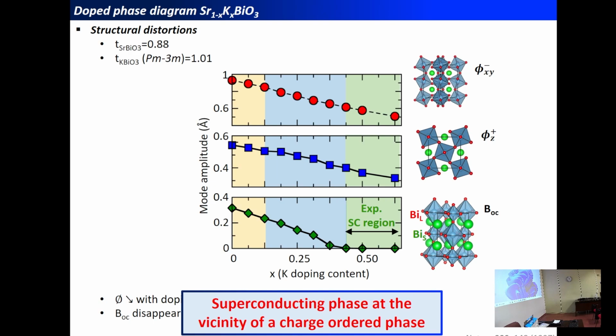Yes? Just one question. If you actually integrate the densities of states, what is the actual value of the charge disproportionation between the two bismuths? If you look at the sphere integrated charge, it's not a very good indicator, because when you integrate the density, there is one sphere that will have more oxygen contributions. So it does increase the number of electrons you would expect to have on this bismuth cation. But from the sphere integrated charges, you see the asymmetry. So it's around 0.4 electrons, something like that. 0.4, yeah, from the sphere integrated charges point of view.